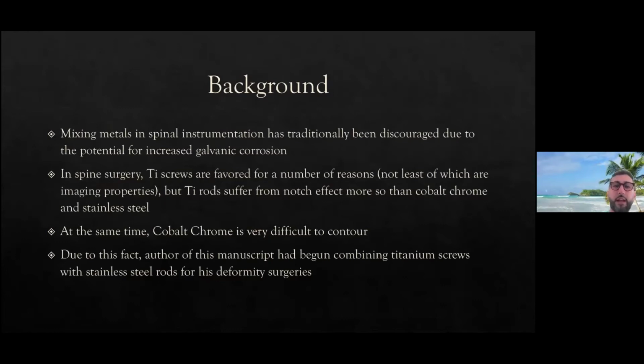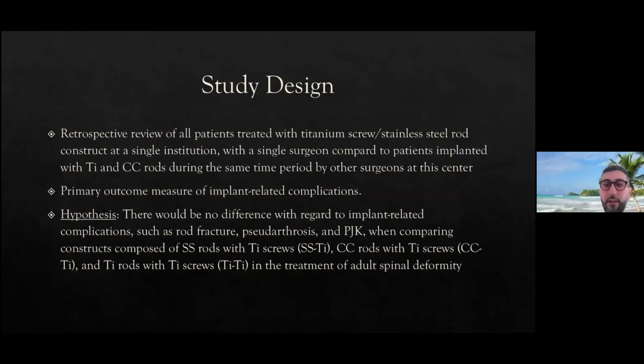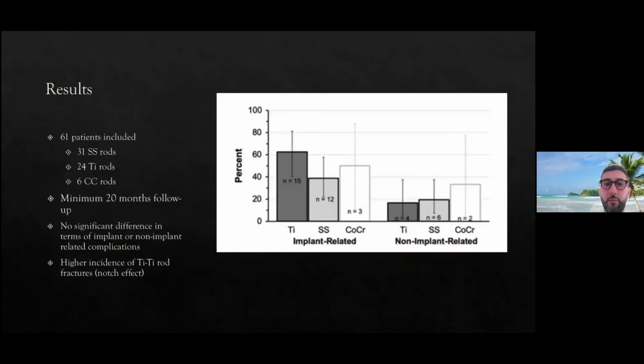Obviously we're beginning to understand why different metals are favored over others, and titanium screws are favored for a number of reasons, but the rods obviously suffer from notch effect, as we mentioned. And so then the question is, should you be using something else for a rod? Cobalt chrome is obviously stronger, but it's more difficult to contour. So this particular author says, oh, well, you should be using titanium screws with stainless steel rods. And he did so for his deformity surgeries.